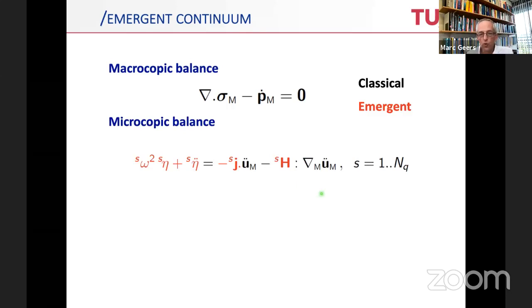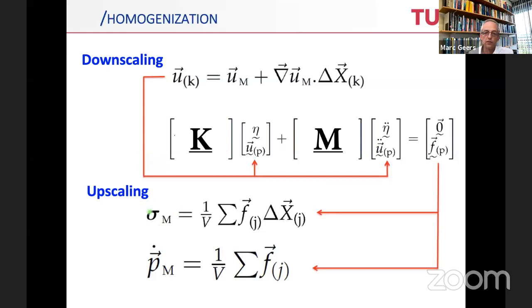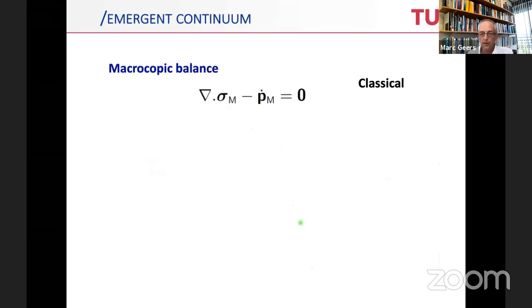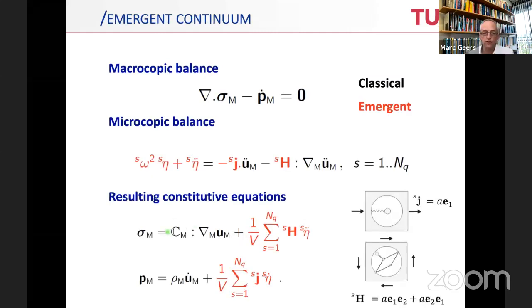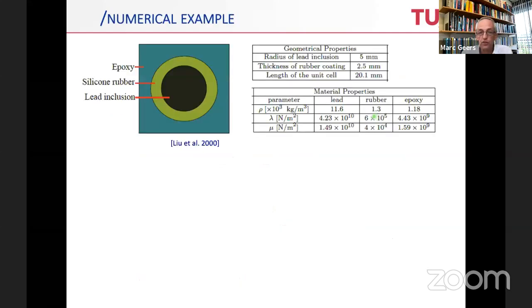There are two coupling vectors and a coupling tensor involved that also enter the constitutive equations. One sheet back, I've shown you how those quantities are determined. If you do the math, you find that the constitutive equations for the stress and the momentum read like this and get two emergent contributions. The standard part is now enriched with a term that is coupled to the etas, and for the momentum, the same thing applies. Here we have a coupling tensor H, and here we have a coupling vector J. This applies for all the modes that you insert into the system. You need to select those modes, and in the problem that we will look at in a second, they're typically selected on the basis of the magnitude of these coupling coefficients, J and H. That's the way we've done it. So it looks like an emergent continuum in which additional quantities need to be resolved at a macroscopic scale.